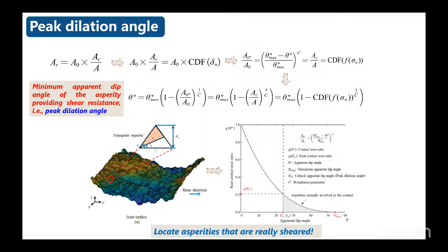After the real contact area ratio is determined, we can predict the peak dilation angle by considering the relationship between the real contact area and the angular distribution of the roughness along the surface. We derived that the peak dilation angle is a nonlinear function of the CDF of the aperture and the 3D morphological parameters denoted by theta star and C. When the peak dilation angle is determined, we can locate the asperities that are truly sheared by comparing the slope of each asperity to the peak dilation angle. The asperity with a higher slope than the peak dilation angle is truly sheared; otherwise, it will not be involved in shear and will not be counted in our model.